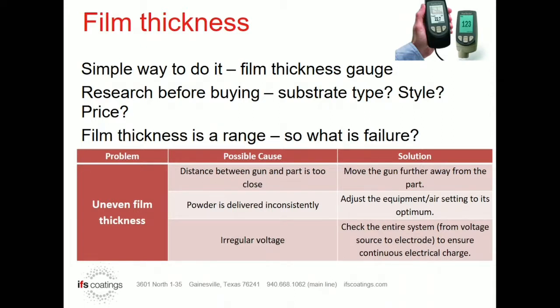Why is film thickness so important? Obviously the visual look matters, but what a lot of people don't realize is that if we make a powder that can handle a thousand-hour salt spray at two mils, that does not mean it can handle a thousand hours of salt spray at one mil. We make a TDS sheet for each product and give you a range of what film build should be, as that is where that product will perform the best.